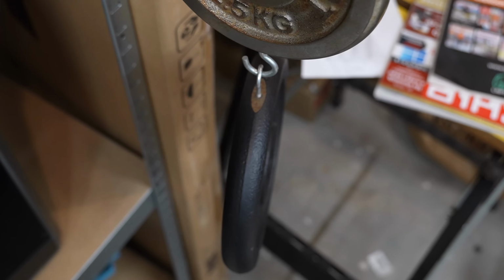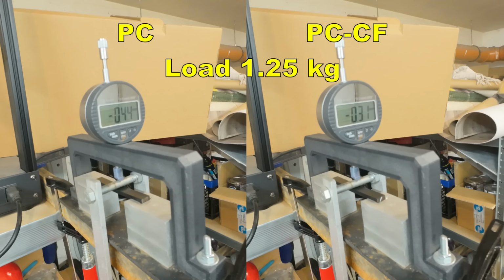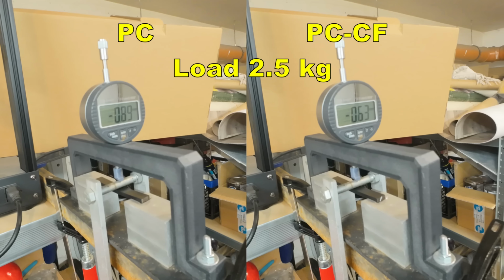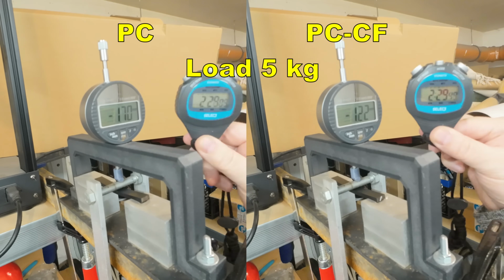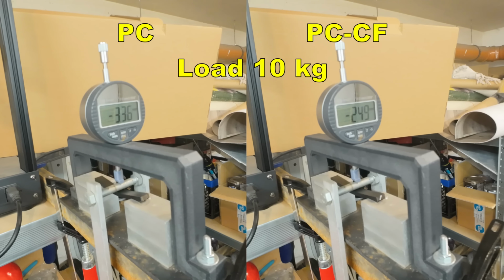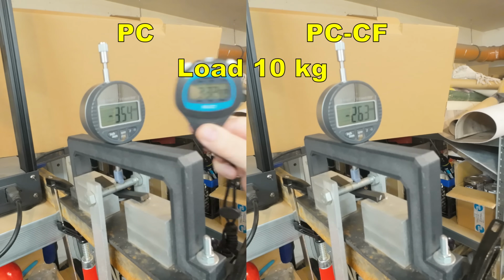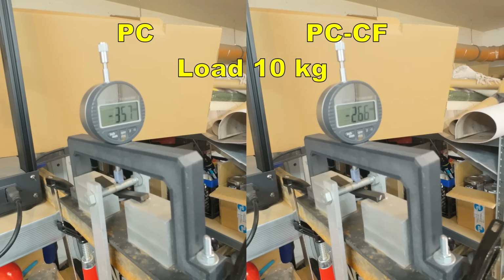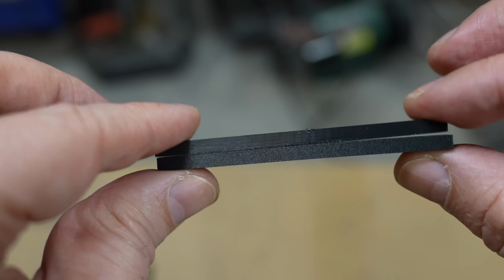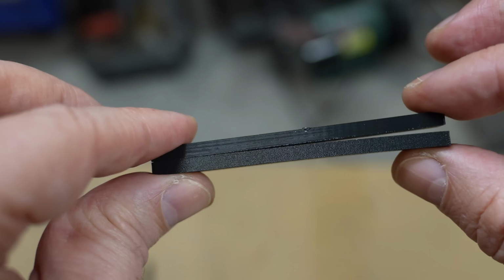3-point bending test where I am placing these loads one by one, and I'm measuring the deformation after 1, 30 and 60 seconds. This is a deformation under 1.25 kilograms. Under 5 kilograms, no big difference, but a noticeable less deformation on the carbon fiber version, and this is under 10 kilograms. Very noticeable permanent deformation on both of them.